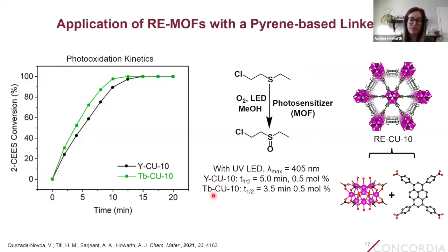So these half-lives are actually among the fastest half-lives that have ever been reported for this reaction to date. And we can do it using only 0.5 mole% of the MOF as catalyst. So we can use a very low amount and then only molecular oxygen and some light to do this detoxification. So much better than incinerating the compound or dumping it into the ocean.